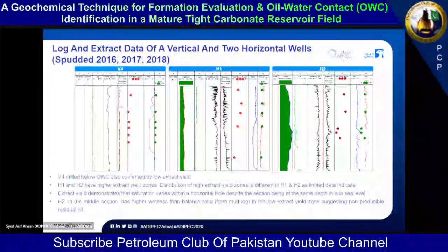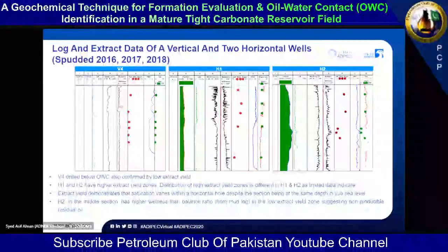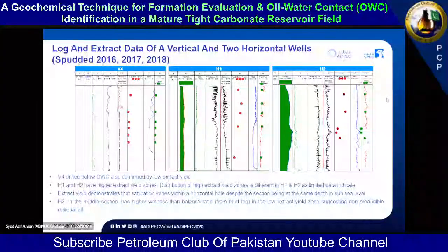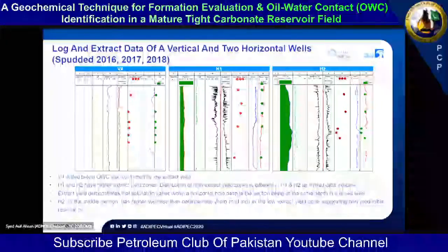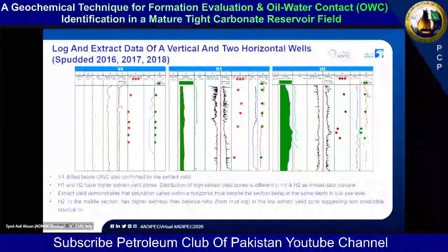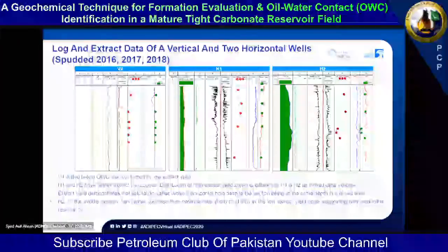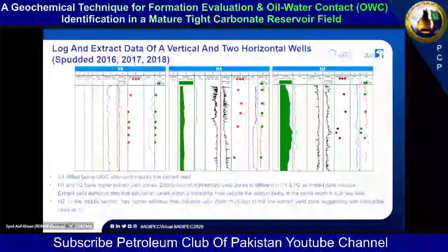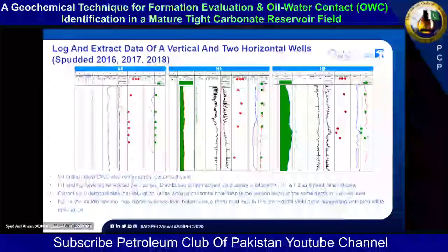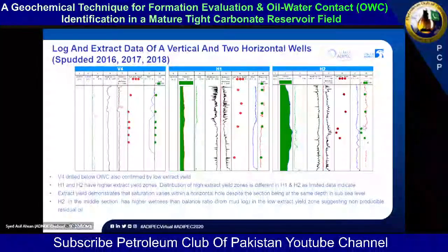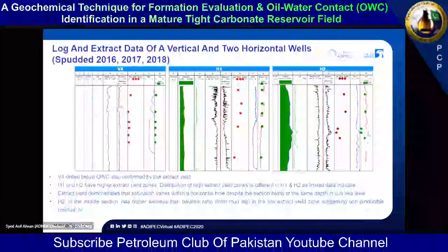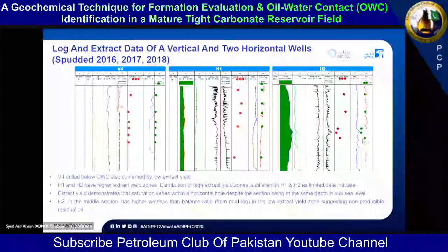However, the pyrolysis-based method is a direct method. There are no assumptions made in the assessment of the water saturation or oil saturation. So horizontal hole H2 is also showing a nice match with the water saturation curve. So these green points are showing, in the horizontal hole, a low in the extract yield. So the horizontal hole somehow entered into a section where there was no oil, and the water saturation must have been very, very high, although water saturation was not measured.